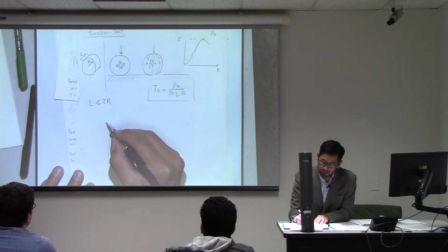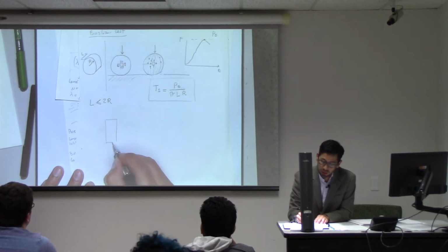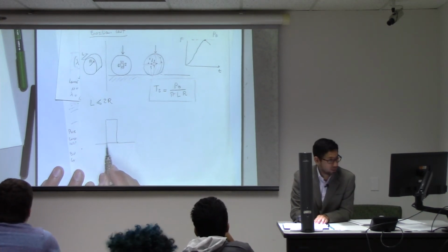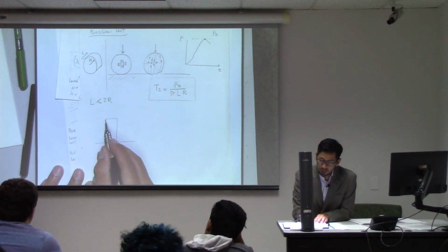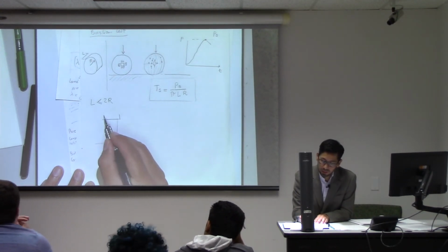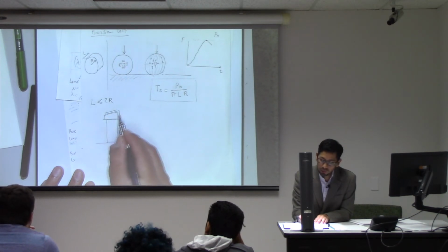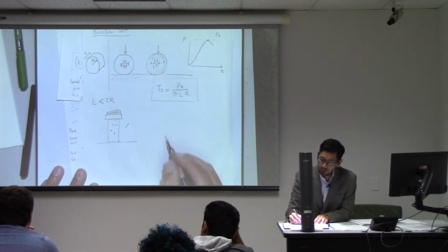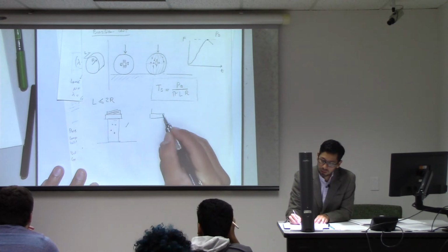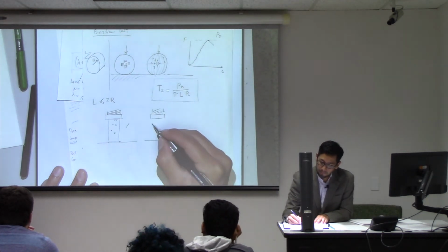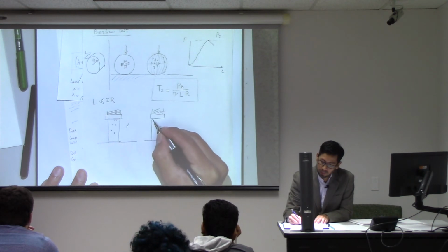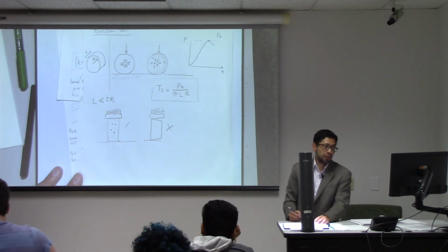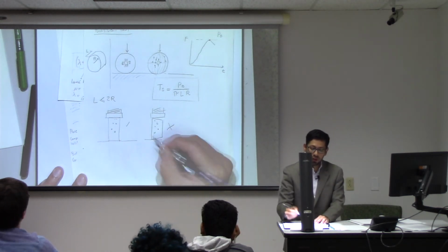So if I look now from the side, you want your lower plate to be parallel to this side, and you want your loading, I think here you have a loading screw, you want your loading screw also to be parallel to that face. This is okay. If you have something like this, that's not going to be okay, all right? Because that's going to give you some other value. It's not going to distribute the force as well.